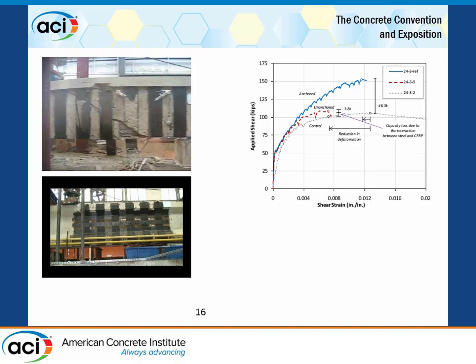So really, I would argue the ultimate here to design would be about 0.006 based on the crack width, essentially, and that's true of columns as well. How you get it to this is by anchoring it. Fully anchoring that strip. So what's fully anchored? What's the embedment depth? What's the spacing? What type of anchor?